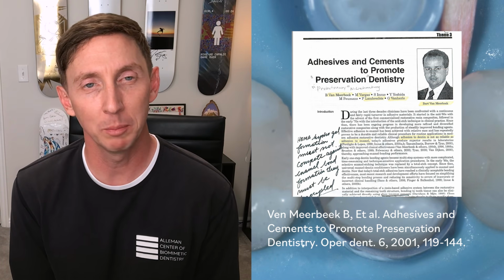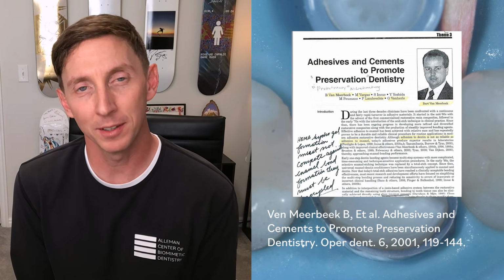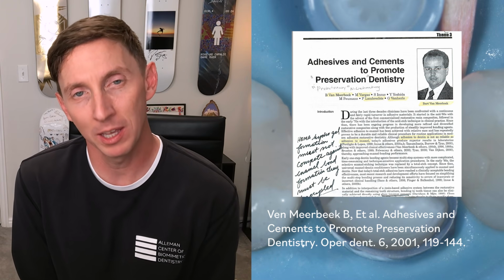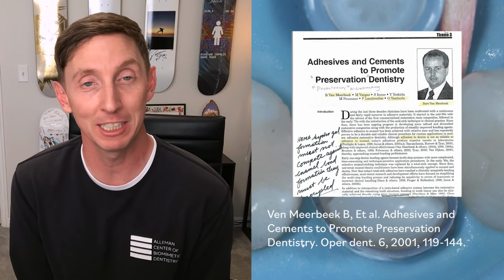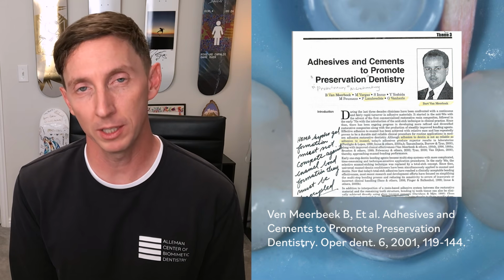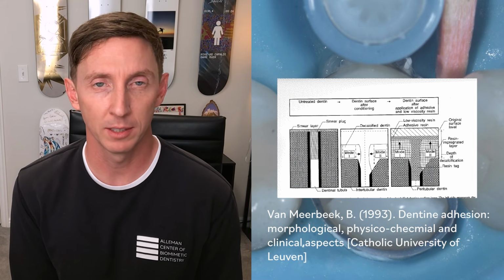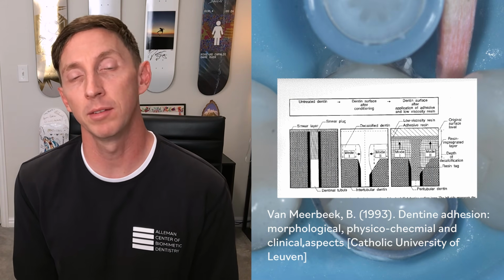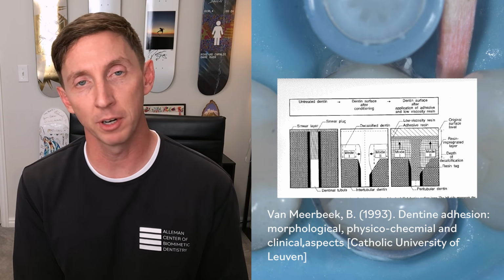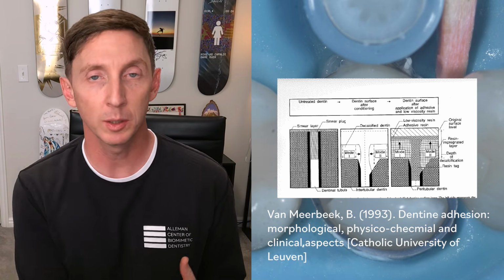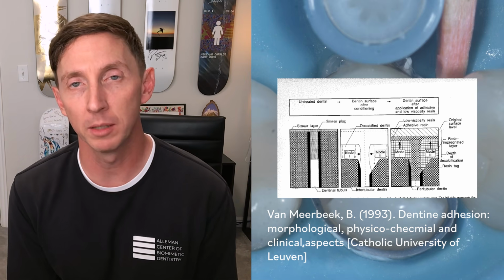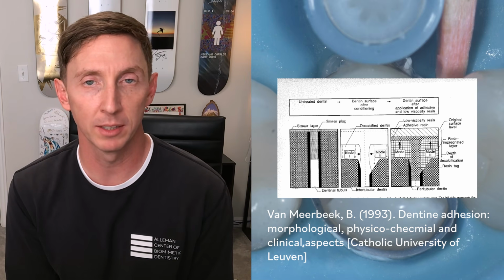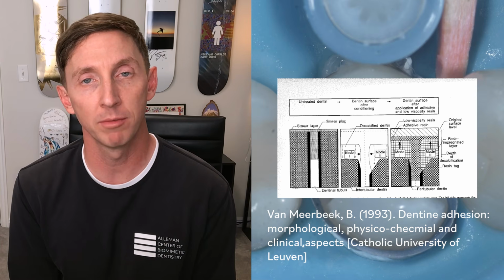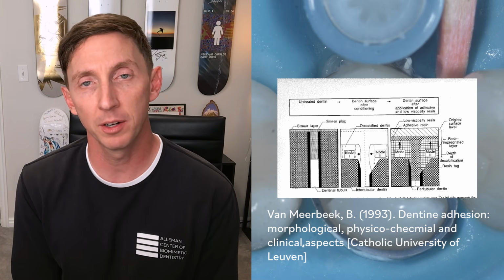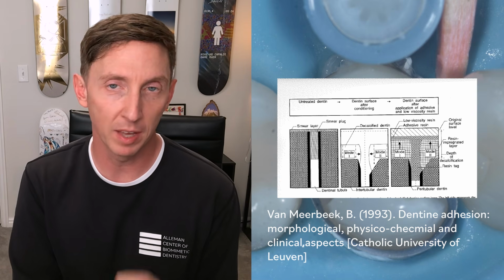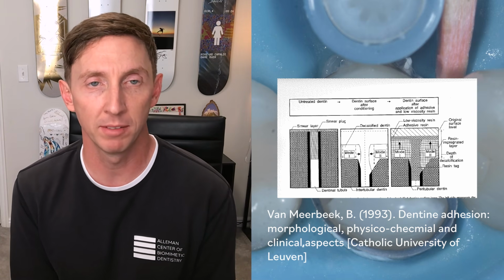Now, this connection can be so strong and the gap between this so small that a bacteria cannot physically enter this layer. With a total etch technique, we have a larger hybrid layer. In other words, the aggressiveness of phosphoric acid allows for a greater penetration of these monomers and subsequent polymers that are created in the hybrid layer. But the strength of the hybrid layer doesn't come from the actual thickness, but rather the very bottom of the hybrid layer, which measures at around 0.5 microns.